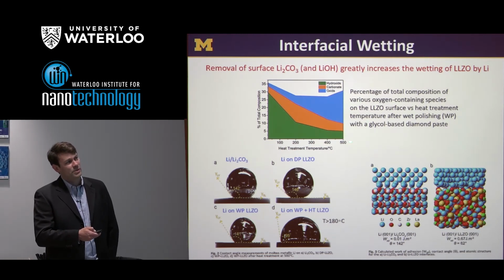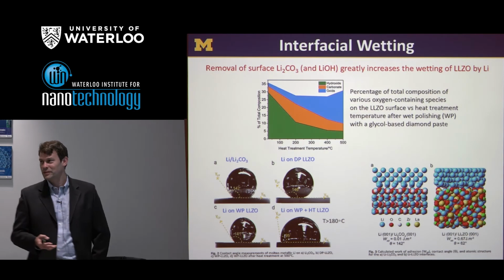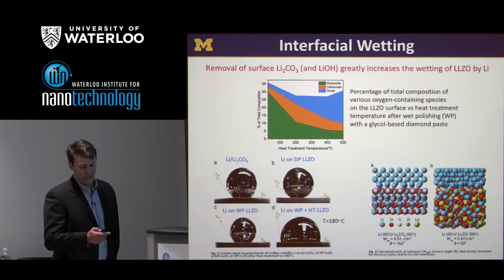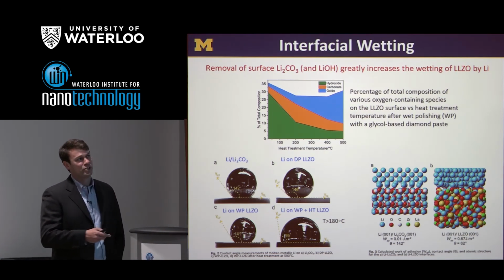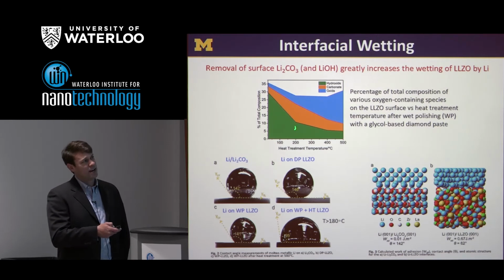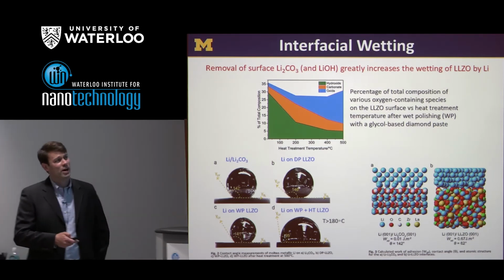And so this is some XPS showing the amount of either hydroxide, which is green, carbonate, which is orange, and the oxide, which is blue. The oxide is the proxy for LLZO. So we'd like to see this blue region be as big as possible and the area of the orange and green be as small as possible.